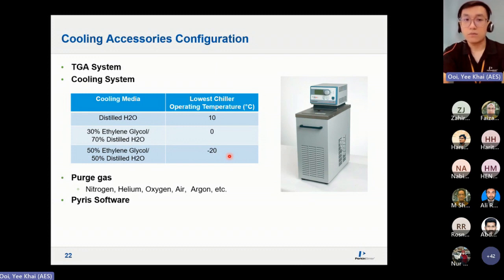So with water, for example, you can start at lowest at 10. If you mix 70% water, 30% e.g. ethylene glycol as a coolant, you can start at 0. So now the water doesn't freeze over at 0 degrees C, okay? If you mix 50% ethylene glycol with 50% distilled H2O, then you can start at -20, okay? So these are things that you need for a TGA run.